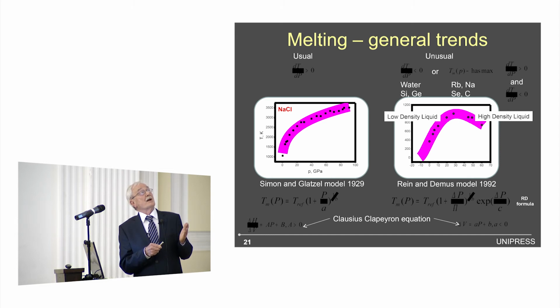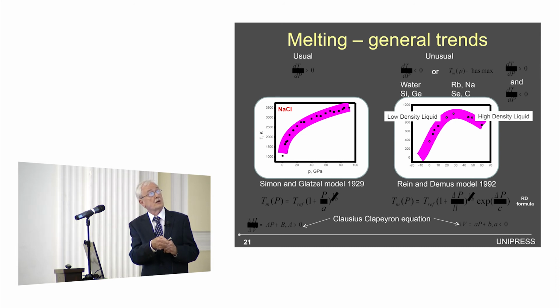You see, various materials are divided into two groups, usual and unusual. For the usual, the melting temperature increases with pressure, and that's the Simon-Glatzel model from 1929, which describes this kind of behavior. And there are unusual ones also. Water was the first example, very well known, where the temperature of melting decreases with pressure. But then other materials joined this group, and it was also observed that these materials are members of a wider group which shows a maximum of melting.